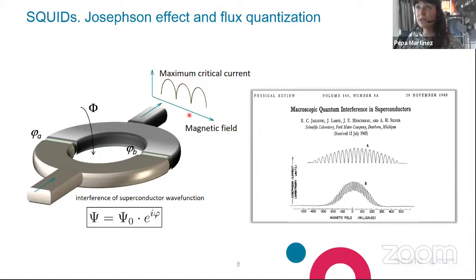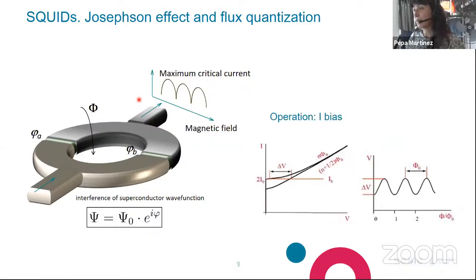This phenomenon occurs in full analogy to what you find when you make the typical experiment in which coherent light goes through a double slit, and you find bright and dark bands as a result. So this by itself constitutes already a magnetic sensor. Here you can see an example of the current voltage characteristic. So you voltage or current bias your device, and you measure the resulting voltage. Once the maximum critical current is reached, a voltage develops and the system starts to dissipate energy.